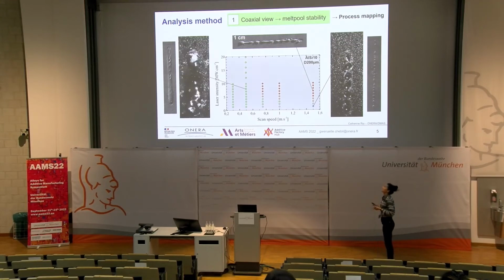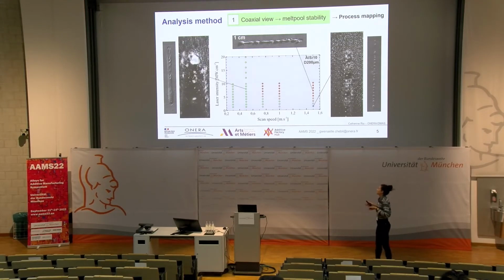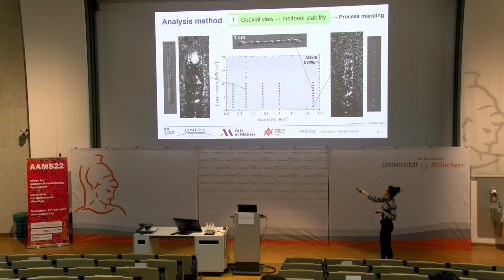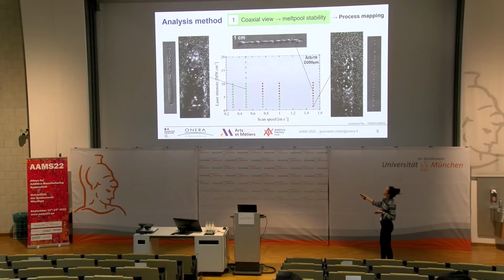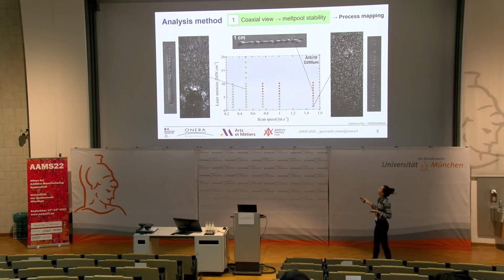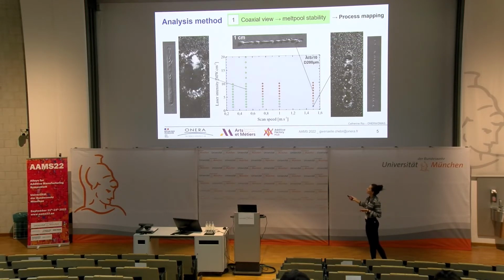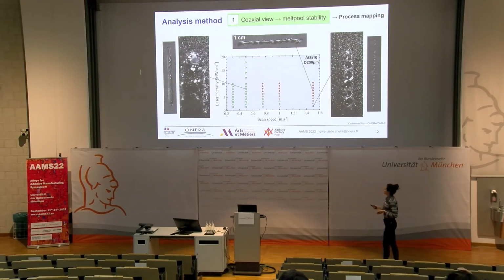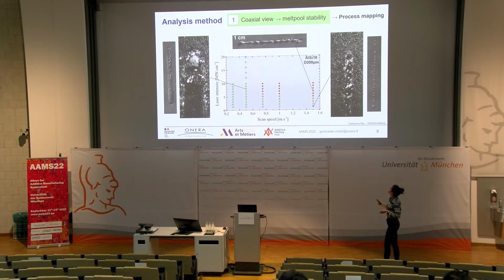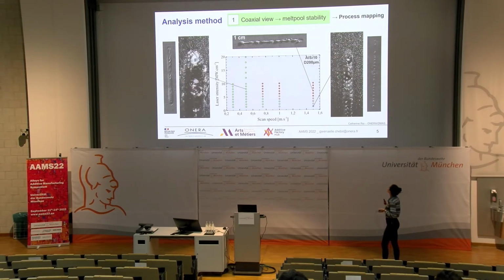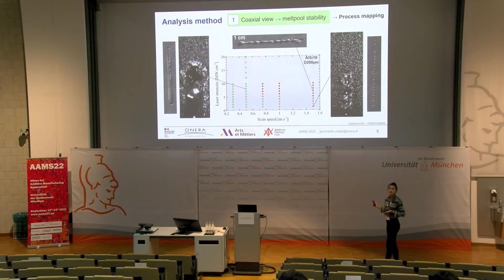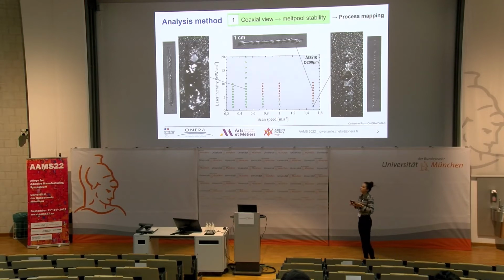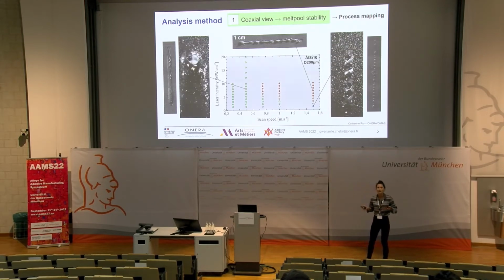Here you have an example of different states, or regions, like a stability thing. Here it's quite a stable state, so we have a stable melt pool, and if we look at the solidified sample in the end, it's quite nice. All the samples are about 1 centimeter long. Here is an example of stable, here you have an example of humping, and here you have a nice example of balling mode. Each point you can see here is a unique set of parameters, so we carry out a lot of analysis.